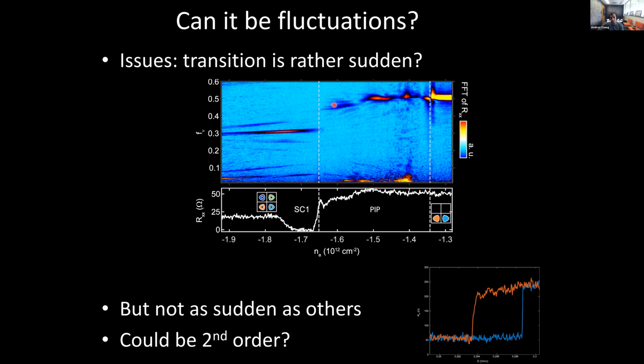On the other hand, it's not so abrupt as other transitions. There are other transitions that actually show hysteresis, where you clearly have a very first order transition. This one does not have hysteresis and generally speaking seems about as mild as any of the other isospin symmetry breaking transitions we've seen. So it could be second order. This is something that we could check. So fluctuations or not, I don't think we can exclude that as a mechanism at this point.